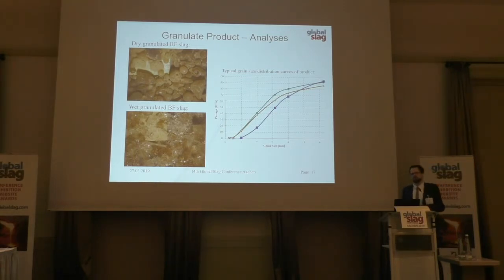What I want to say first is that we sometimes start the plant with what we call pre-filling. This means we fill wet granulated slag into the granulator, and then we mix it up over the trials with dry granulated product. So we have a sample where we have done this investigation showing it's not 100% free of wet granulated product, but the calculation says it must be far above 90% dry granulate concentration. On this slide, at first view, you can see the largest difference of dry granulate compared to wet granulate. We have a different shape: a round shape, and a very smooth surface compared to the wet granulated slag.